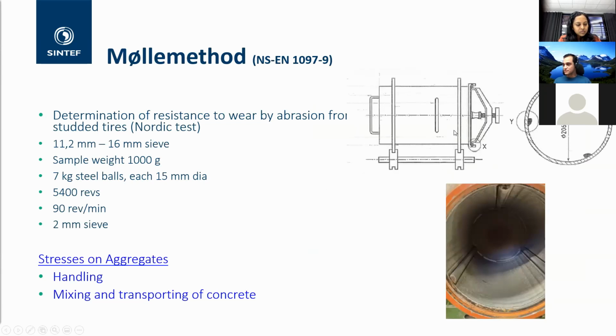This is the equipment used for the Molle method, which has a diameter of 206 millimeters and some ribs on the inside of the drum, same as the Los Angeles test, but it uses a sample of 1,000 grams between 11.2 and 16 millimeters. And 7 kilograms of steel balls are used, and they go through 5,400 revolutions. And we again asked ourselves and discussed, is this the right amount? Isn't it too harsh for the aggregates? Because the stresses on the aggregates that we are talking about are the handling with a belt loader or a wheel loader, and mixing in the concrete drum and transporting, so the revolutions in the concrete drum. So we thought that this is a bit too harsh for the aggregates.